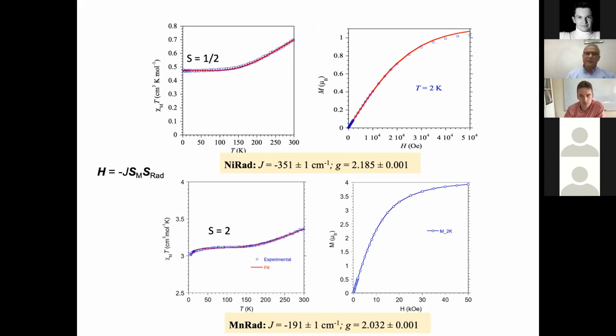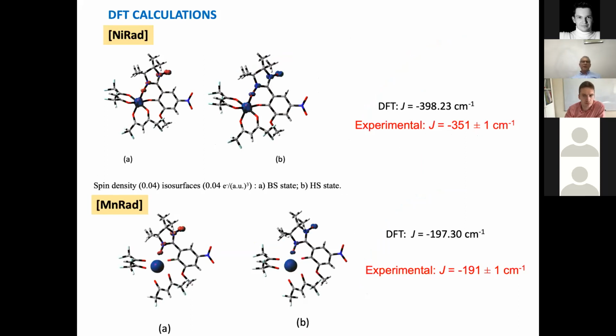So what about the magnetic properties? The exchange interaction is quite strong, so the metal ions are coupled even at room temperature. The most interesting feature to be observed is that we have a large plateau here that indicates that we have only this ground state, S = 1/2 for the nickel complex and S = 2 for the manganese complex. The fitting of the experimental data leads to the following values of the exchange parameters. These data can be theoretically rationalized by DFT calculations, and we found theoretical values close to the experimental ones.